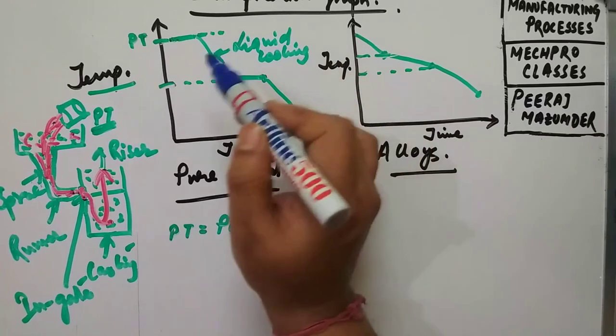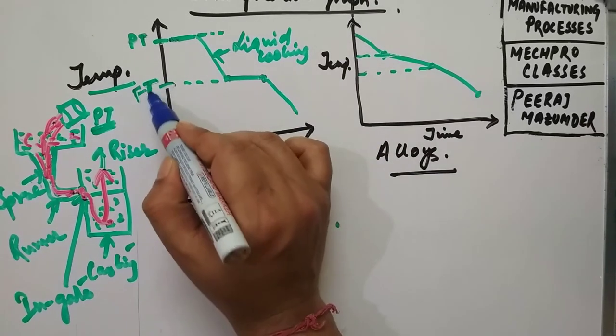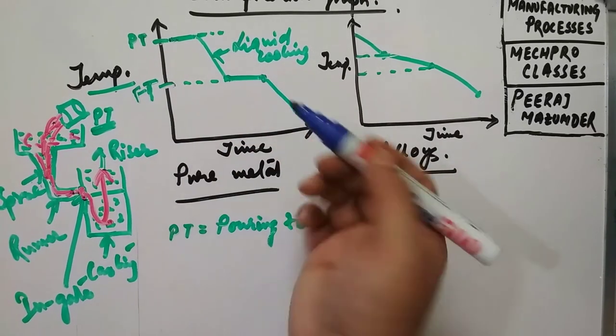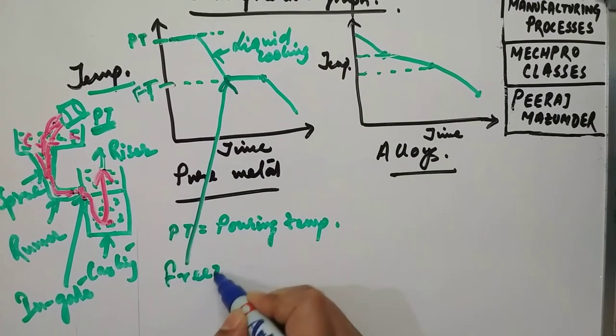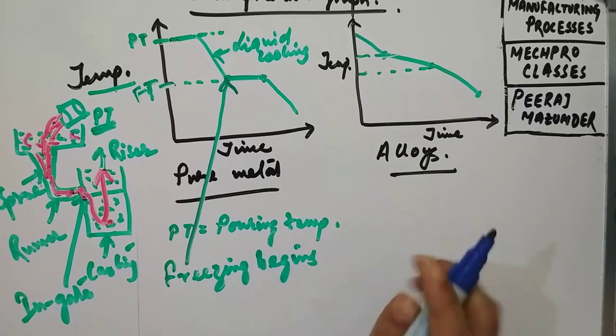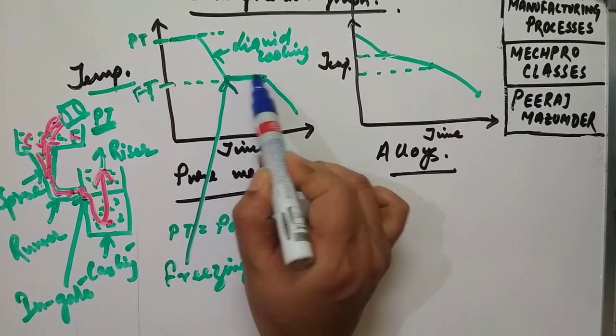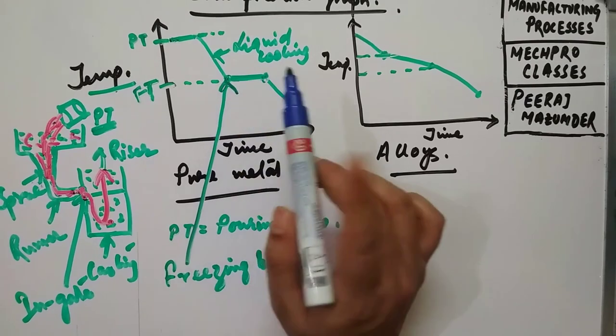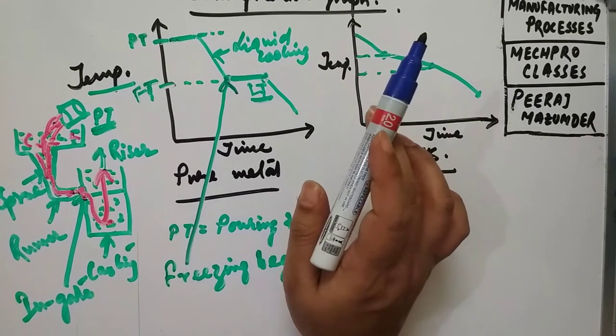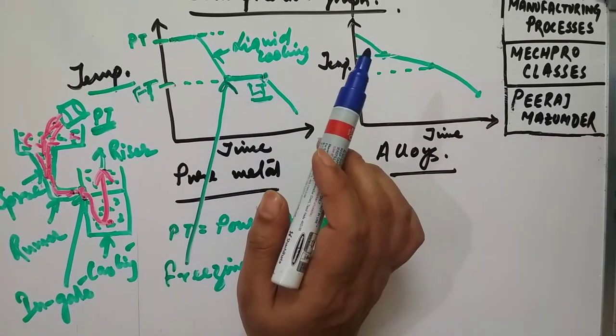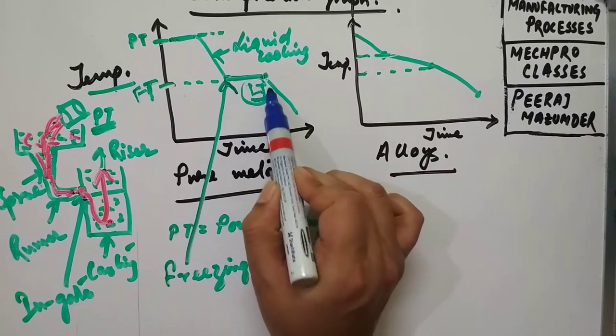This temperature is generally known as the freezing temperature, FT. This is the point where freezing begins. And this particular line is the phase change — given as a straight line for pure metal. Here only latent heat will be removed. That's why it gives you a straight line, as because there is no change in measurable or sensible temperature — we will only have loss in latent heat. The phase will change from liquid to solid.